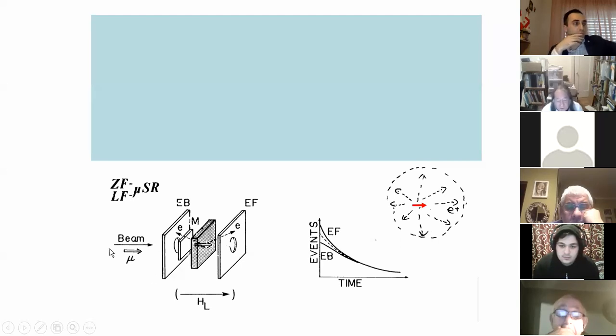You can apply the field parallel to the spin direction, and that is called longitudinal field, and that would create something comparable to the condition of nuclear magnetic resonance. But still, we do not have to have a radio frequency (RF) field, and we can do very much similar things to everything done by nuclear magnetic resonance without having radio frequency. And so this can be done in any material. We can implant muon to various different systems. So that is the advantage of this technique.